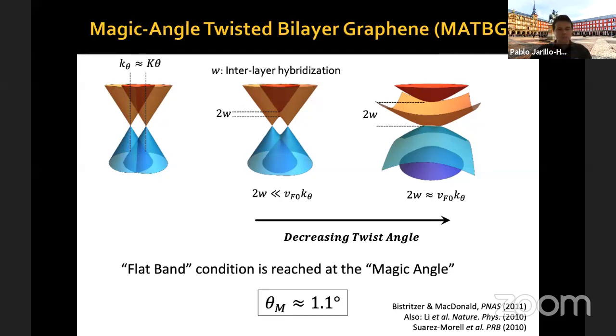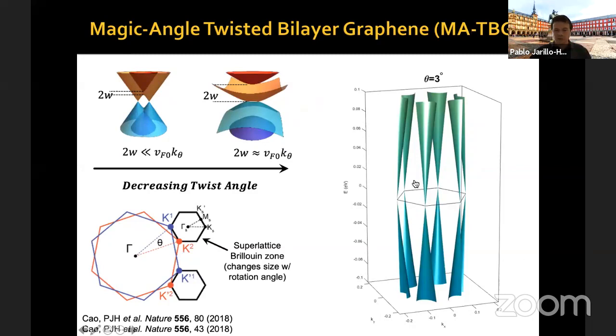Now, this thing that I mentioned is sort of a cartoon. Let me show you an actual calculation of the electronic structure. Again, these are the two graphene reciprocal spaces for layer one and layer two. If you join the corners of the Brillouin zones, you can form the superlattice Brillouin zone. You can see it's a small superlattice Brillouin zone because the moiré pattern that you form is a long wavelength moiré pattern. In this video on the side, I'm going to show the energy versus momentum for twisted bilayer graphene, for an angle of 3 degrees. I'm going to run a video now, but what you can see is that for 3 degrees, within this energy window, this basically looks like Dirac cones.